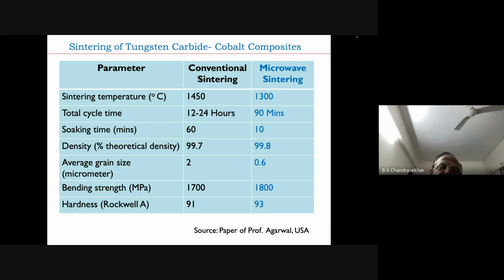Now look at the cycle time. With the microwave, it is only 90 minutes. What was taking 24 hours or overnight is reduced to 1.5 hours. Soaking time is only 10 minutes rather than 60 minutes. The reason cycle time is so low is because you can go to a very high temperature very quickly, since microwave power can increase very quickly, and theoretical density is also more.